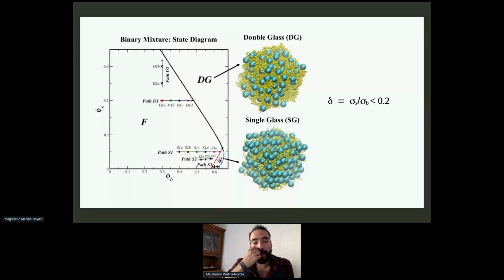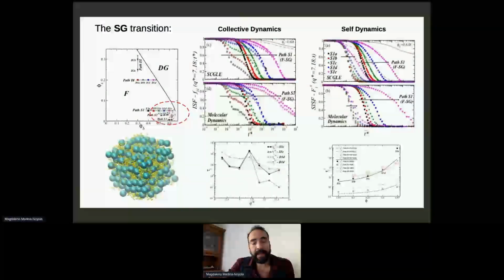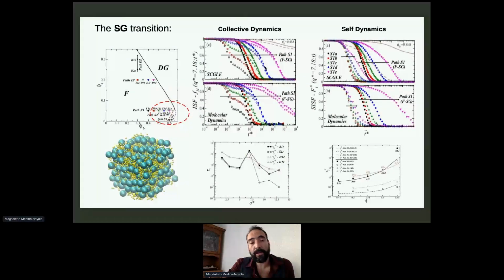But upon the exchange of small and big particles, one can also form a different kind of glass with different physical properties, which is formed by a majority of small particles, which have slow dynamics, and which more or less slave the big particles. So the big particles become slow because the majority of small particles are becoming a glass. We actually characterized this, combining the techniques that Marco was describing before, but also combining extensive numerical simulations based on molecular dynamics. We characterized, for instance, how the transition approaching a single glass state looks.